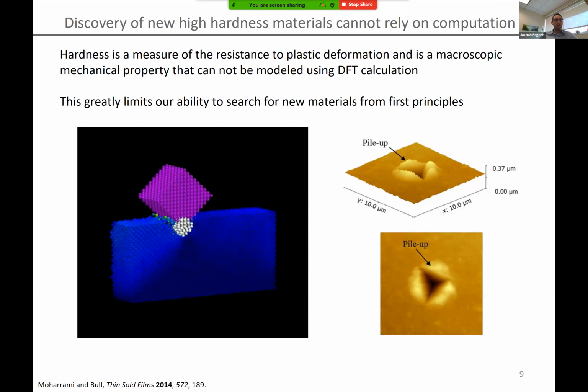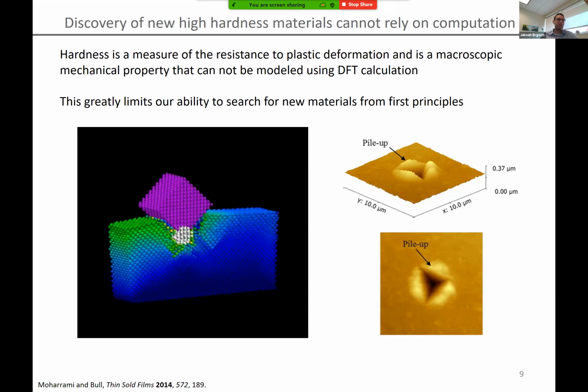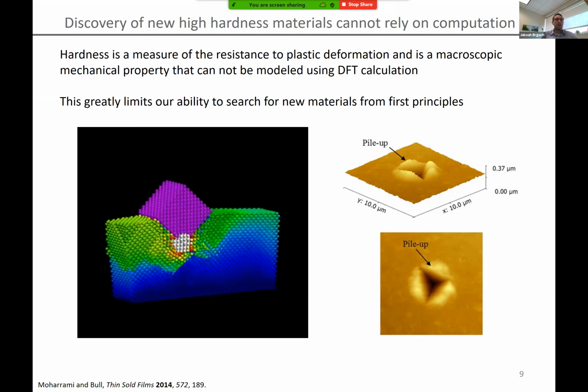The blue, these are residual forces. The blue forces, or residual forces, start to become green and red—these are high amounts of residual forces. You can see that the process of indentation is not even captured in this multi-thousand atom molecular dynamics simulation.